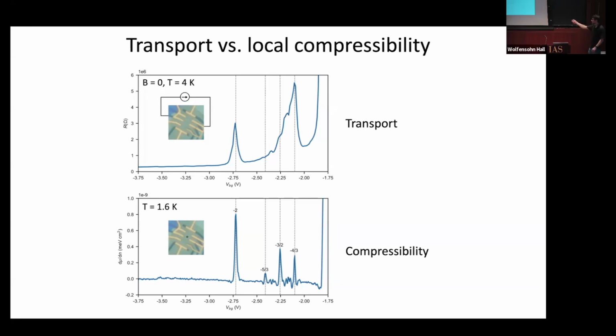No, so okay, this is done in a 4K dunker. That is, we dunk the whole sample in liquid helium. So I don't have data to show you at 1.6 Kelvin in transport, but what happens is that because the electrical contact is challenging, the entire resistance goes up, and if anything, these peaks are often swallowed up by the insulating behavior that you get from the semiconducting band gap as you approach the band edge. So actually it gets worse in transport. At low temperature, the charging becomes harder, and it's not that these peaks are appearing because of the low temperature, it's that these peaks are there because the technique is really a better way of looking at these samples.